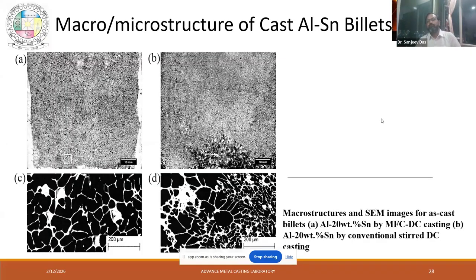Now again, we have added tin. Suppose we are adding a heavy metal. The tin is very heavy, the density of tin is much higher than aluminium. So if you don't use a rotor stator device, then the tin will settle at the bottom. But if you use it, it is equally distributed inside the billet. So you can beat gravity, you can beat the columnar grain formation, by the forced convection machine.